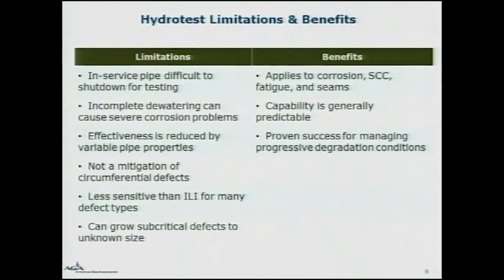The use of hydrostatic pressure testing for in-service pipe does have limitations. First, the pipeline has to come out of service for a hydrostatic pressure test, which may not always be feasible. For example, the pipeline may be a single directional feed to a downstream area, which may represent too large of a load for utilizing either a temporary supply or a bypass of the affected section. Second, and of equal importance, is that incomplete dewatering can lead to future internal corrosion.